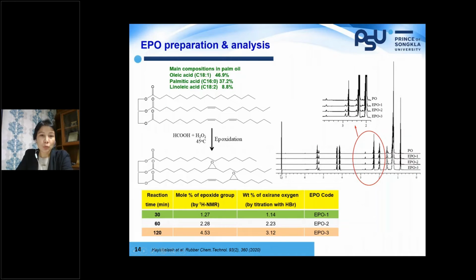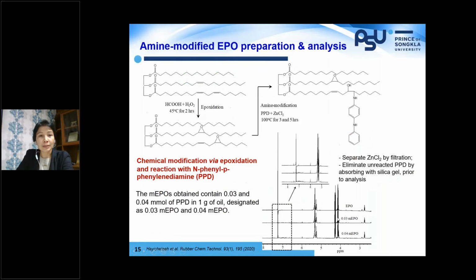Look at the example of the work that we did on palm oil. We took palm oil that's available in the market and did simple chemistry, the epoxidation, using hydrogen peroxide and formic acid. Under mild conditions, you can convert this unsaturation site to an epoxy ring, and we can prove it by NMR spectroscopy. By varying reaction time, we obtained different mole percent of epoxy group, and this can also be characterized by the titration technique. And we have three different levels of epoxy here.